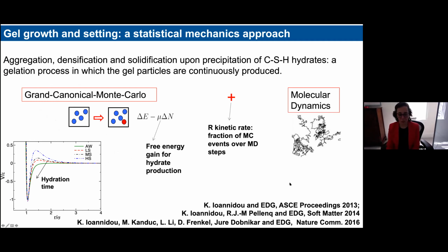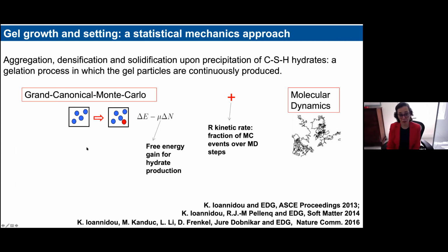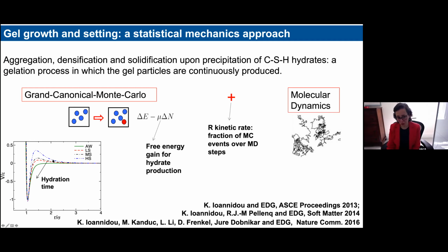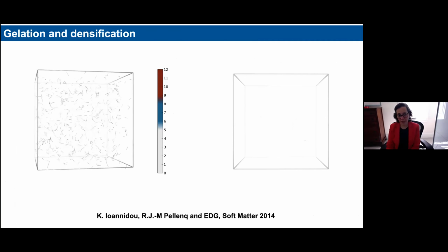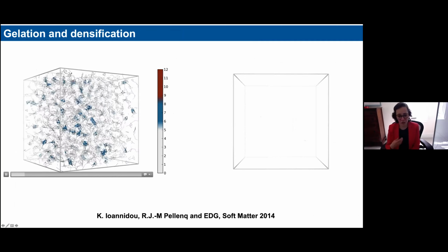In the first study that I'm showing you now, we fixed one type of interaction, for example the one with a relatively higher intermediate repulsion, which should correspond to very early stages of the cement hydration. Then we study how the precipitation leads to different types of gels for this interaction. Then we switch to an interaction with less of this intermediate repulsive part, so that it becomes more and more purely attractive, which should correspond to later stages of hydration. In this movie, what I'm showing you is the precipitation as it occurs during the simulation.